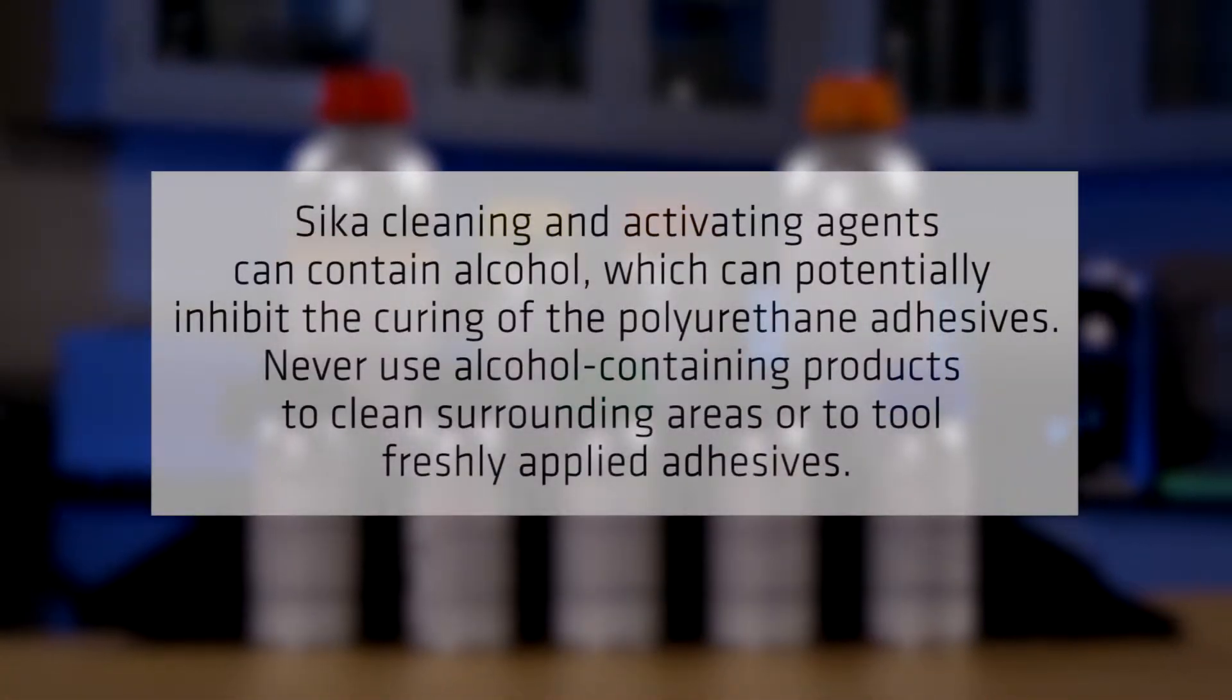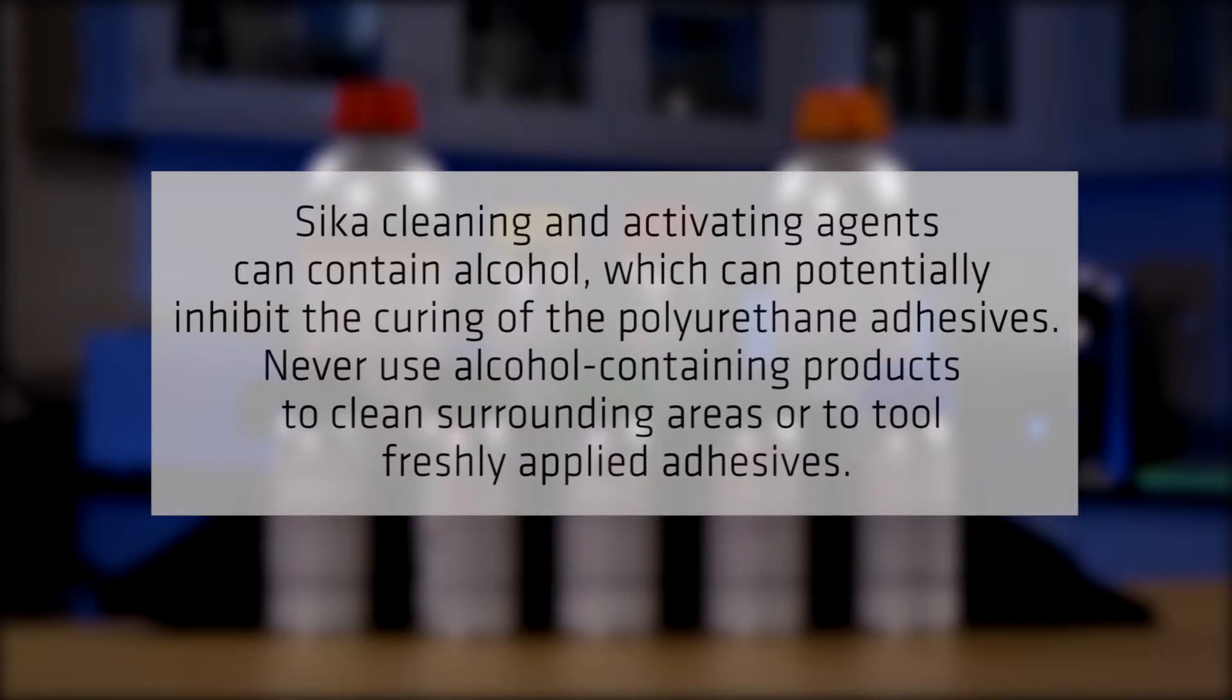Sika cleaning and activating agents can contain alcohol which could potentially inhibit the curing of the polyurethane adhesives. Never use alcohol containing products to clean surrounding areas or to tool freshly applied adhesives.